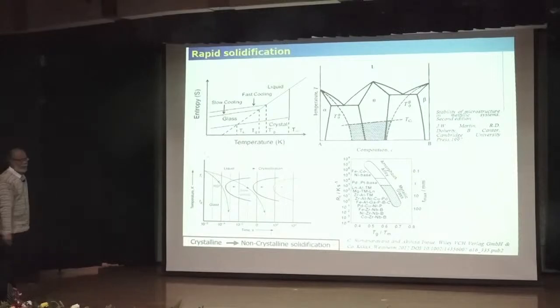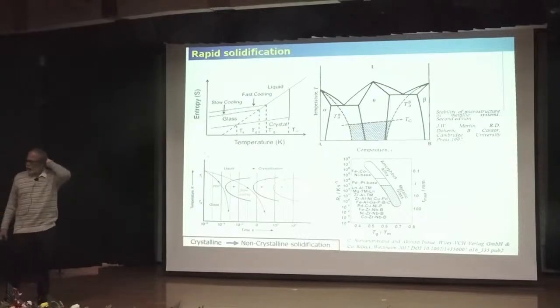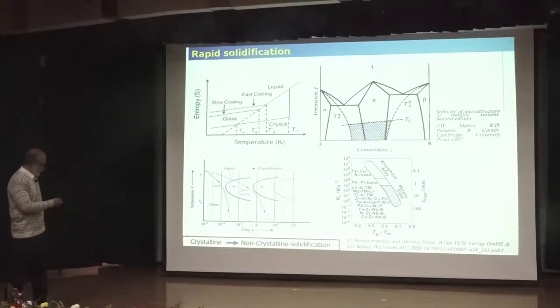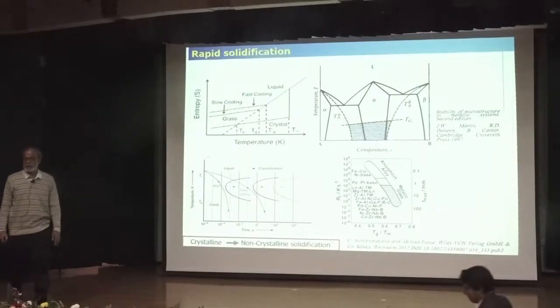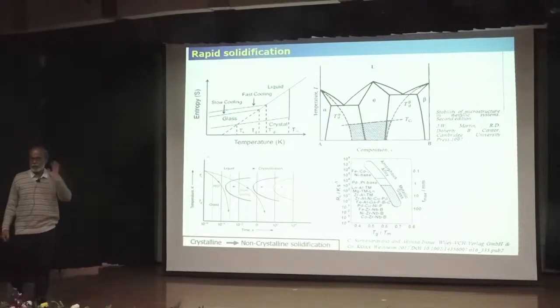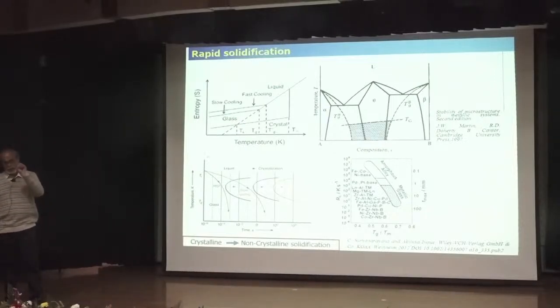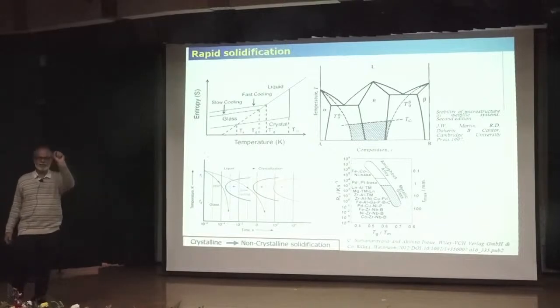People found that liquid can be supercooled even below melting temperature if you increase the cooling rate, right? So in 1948, Kauzmann proposed that there must be a temperature, the Kauzmann temperature, below which you can cool the liquid and you can have an amorphous phase. And Pol Duwez at Caltech produced the amorphous phase, but it was a strip, small thickness, with very high cooling rate.